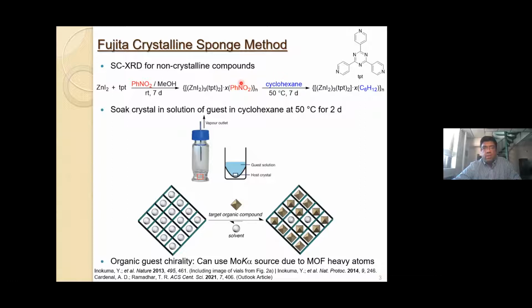And that's because nitrobenzene has a strong affinity for the pores, and it's going to be hard for the target molecules to be able to displace the nitrobenzene. So then you take these crystals, you put them into cyclohexane, heat at 50 degrees centigrade for another week, and then you're able to get crystalline sponges that are viable for the technique.